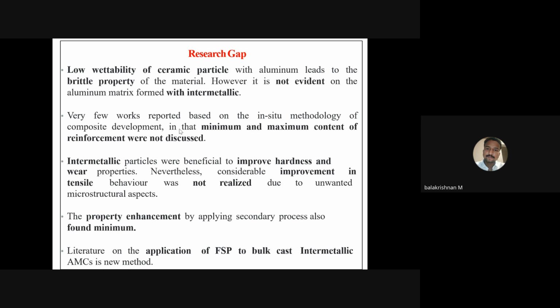Then intermetallic particles were beneficial to improve the hardness and wear property. Then improvement in tensile behavior was not realized. Whenever a lot of researchers researched in the intermetallics area, the improvement in tensile behavior was not realized, though a few papers mention that so-and-so intermetallic particles in so-and-so parameter have improved the tensile strength of the particular material. So the property enhancement by applying secondary process was also found to be minimum. Most papers say that these are the secondary processes, but how the particular product was enhanced, the property enhancement was very limited. So it has to be found out.